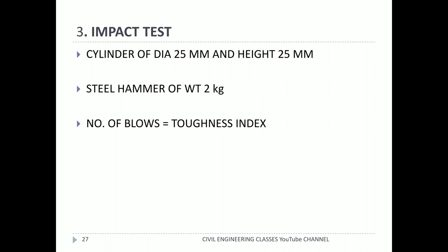Next test is the impact test. For the impact test, the sample taken is a cylinder of 25 mm diameter and 25 mm height, and a hammer of 2 kg is used to give the impact. We know toughness is the resistance towards large impact. The number of blows that is required to break the cylinder is taken as the toughness index value.